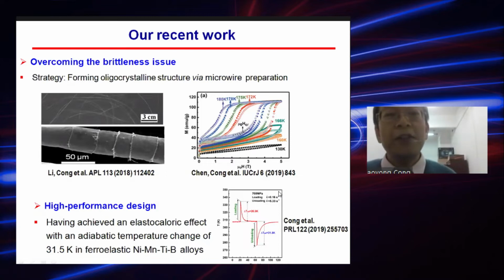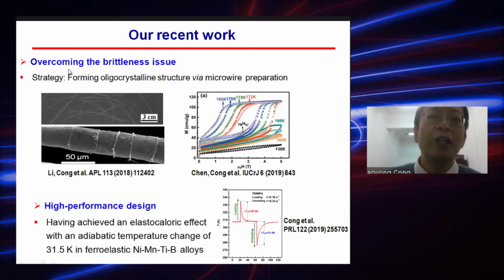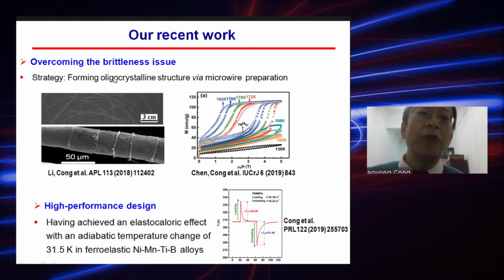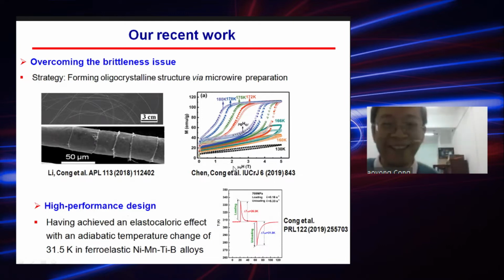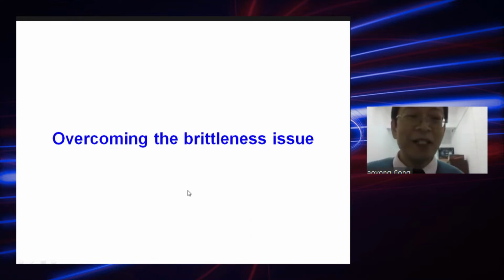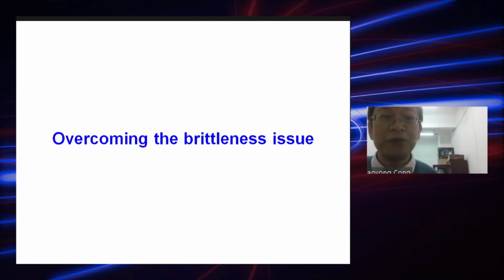Our recent work mainly focuses on two points. The first one is overcoming the brittleness issue, for which we use a strategy of forming oligocrystalline structure through microwire preparation. And the second part is high performance design, and we have got elastocaloric effect with adiabatic temperature change as high as 31.5 Kelvin. The first part is more related to materials, and the second part is more related to physics. So now the first part, overcoming the brittleness issue.